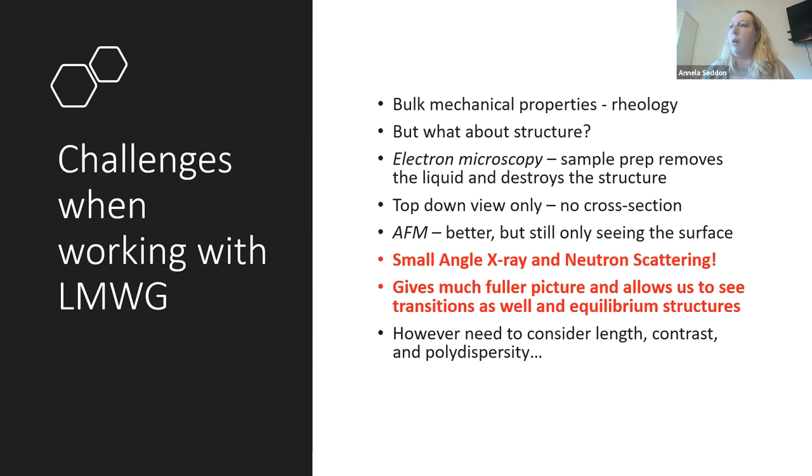You can do cryo-EM, and I'm going to show you some cryo-EM on some of these systems later. But there's a second problem, and that is the way we do a TEM measurement, we're looking from the top down. And if we look from the top down onto these nanoscale fibers, all we're seeing is effectively a two-dimensional projection of a three-dimensional material. So it tells us nothing about the cross-section. And actually, we'll find out later that cross-section is really important in terms of structure.